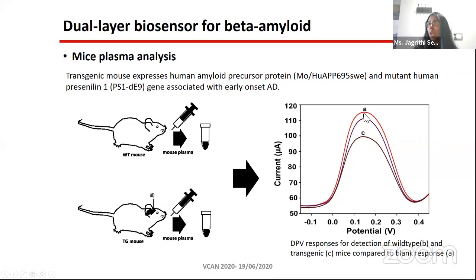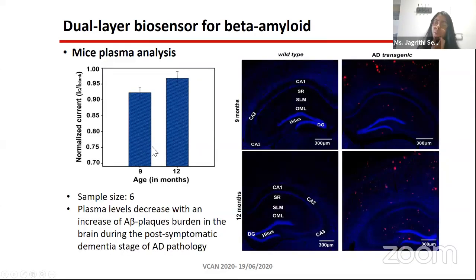So as you can see, the only shift that we see, the C here represents the transgenic mice. So the transgenic mice shows a significant decrease. And the other wild type mice did not show that because it does not have much beta amyloid. And we also carried out an age-based study with a mice plasma sample.